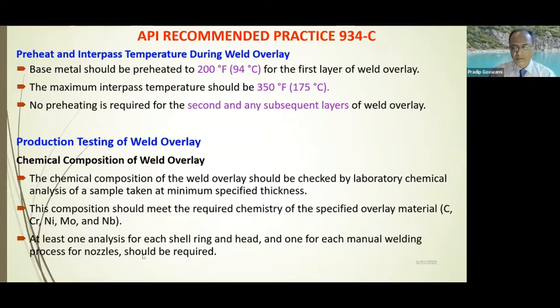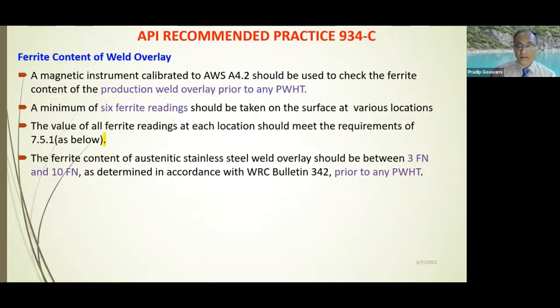What it means is that for every weld you do on this equipment, you need to do a chemical composition check at some stage of fabrication, preferably just at the end of the final fabrication. And the ferrite content, as I mentioned, typically should be between 3 to 10 FN.